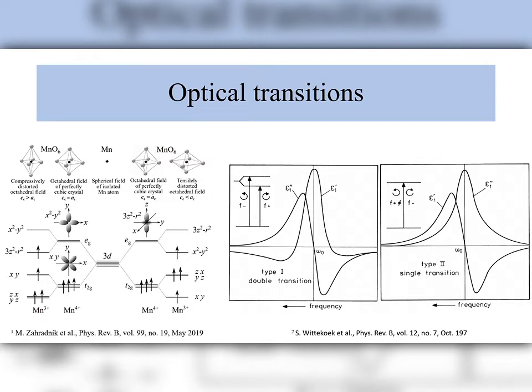On the left side of the slide, the splitting of the manganese 3D energy levels is illustrated. At the center, we have the 3D levels of an isolated manganese atom. Next to it, we have the split levels of the atom surrounded by 6 oxygen atoms in a perfect cubic crystal. To the sides, we have the effects of epitaxial strain on the energy levels: on the left side the compressed crystal, and on the right side a tensile distortion to the crystal.